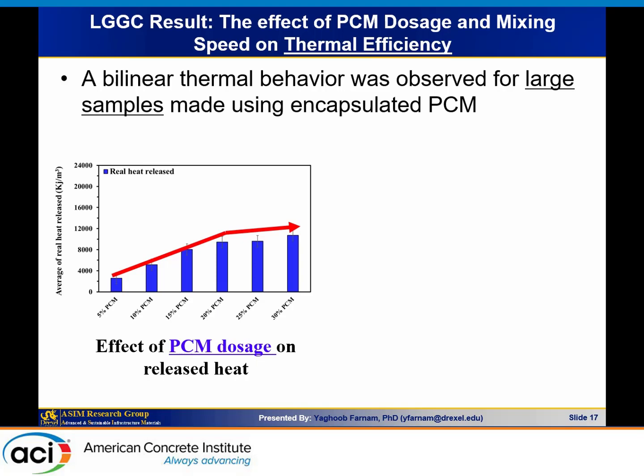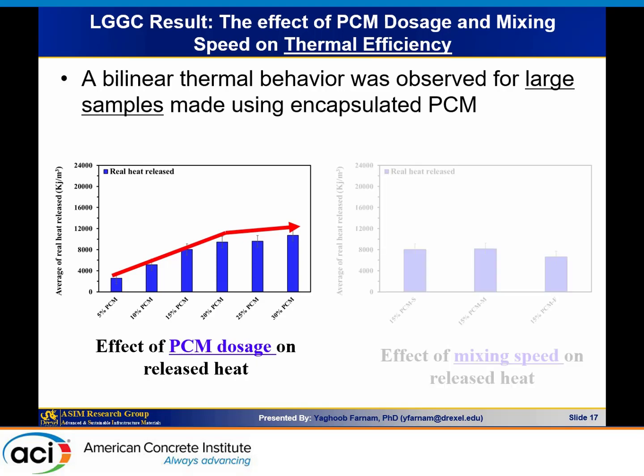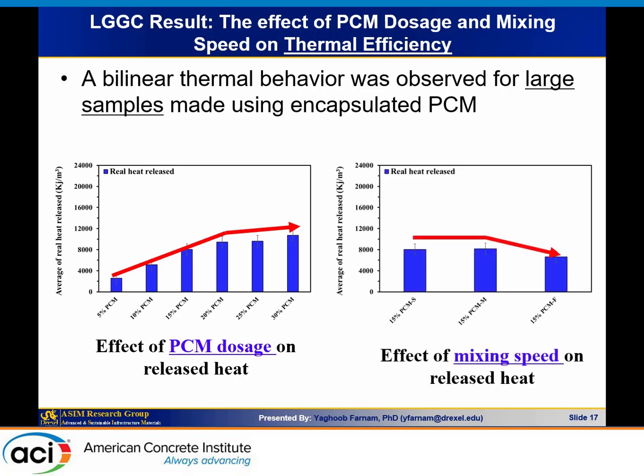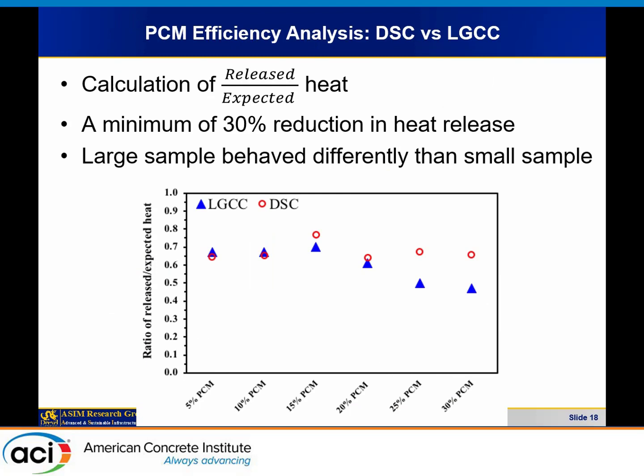And this is maybe partially coming from using a large sample, or maybe partially from the assumption that we made in LGCC. But the type of behavior that we get here is a bilinear effect. So it might not be effective to increase the PCM dosage too much. If you look at the mixing speed, again, we saw something similar, a bilinear effect. And again, here, it might be partially from the LGCC testing protocol, or it might be because of the sample size.